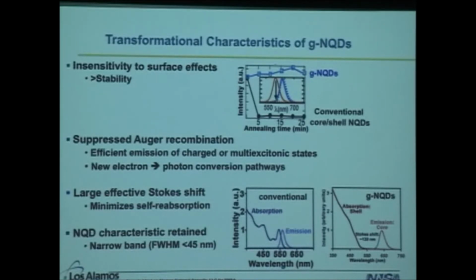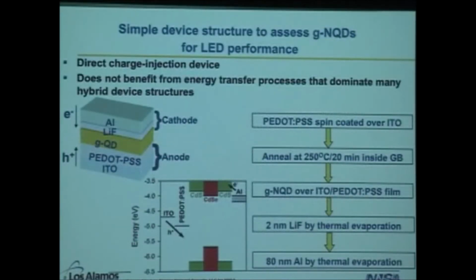In a conventional quantum dot, the energy separation between the absorption onset and the emission peak is very, very close. In the giant dots, the primary absorption comes from the shell, which is significantly bluer than the emission from the red core. So we have a large effective Stokes shift. And this actually plays a role when you use these as phosphors, and I'll get to that in a moment. We are still able to retain a reasonably narrow band, although not as good as a conventional quantum dot. The giant quantum dots are typically 40 to 45 nanometer full width half max.